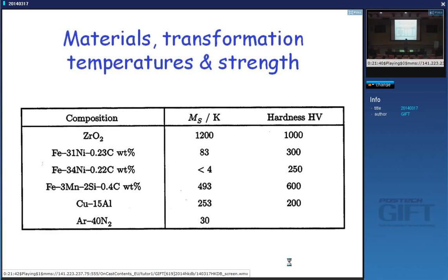That isn't strictly true, because both are cubic. BCC has even more, because the slip plane is the 110 slip plane, and 111 directions, but also 112 directions, 113 directions, and so on. We call that pencil glide. So there's a really interesting reason why carbon has a much bigger effect on hardening ferrite than on hardening austenite. And we'll come back to that later on.